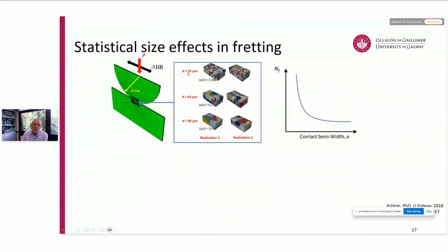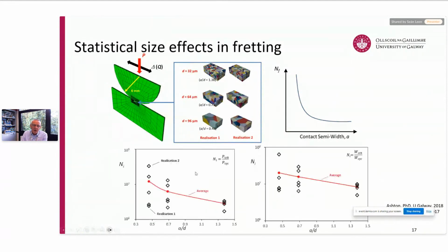So you can see we're looking here at different grain sizes, basically, and the grain size to the contact width basically means that we can represent essentially different contact sizes. And then what we see from that, we can look at how the contact size basically affects crack initiation. And if you look at the results in the bottom left and the bottom right, you can see that the life gradually, as we reduce the contact size, so the A over D, as that gets smaller, the average life increases.